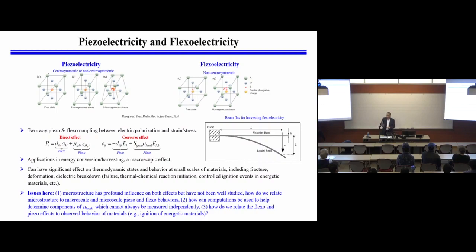Even for isotropic materials, for those of you who are taking continuum mechanics, you know that isotropic fourth order tensors have only up to three independent constants, just like the linear elastic modulus. For isotropic materials, it can boil down to ultimately two independent constants, the Young's modulus and the Poisson's ratio. So for flexoelectricity, this tensor also works out to be only two parameters. But even then, they are still very difficult to measure.